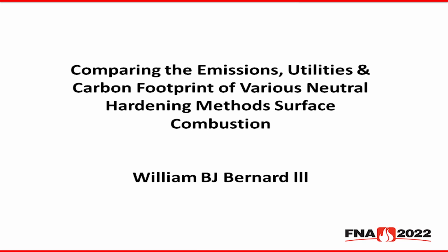So here's just an example of a calculation between RX, endothermic atmosphere, versus nitrogen methanol, using the numbers we just presented. If you're using gas firing or electric to heat the gas, this is for 400 standard cubic feet per hour of endothermic gas. Whether it's made from nitrogen methanol or made from RX, it's 400 cubic feet, and we're at a 1700 degree furnace. So the feedstock, when it comes out of the generator, RX has 4.76 pounds of CO2 per hour if it's made using natural gas heating. Electric heating is going to be about the same, might be a little bit more, a little bit less, depending on your electric heat source.